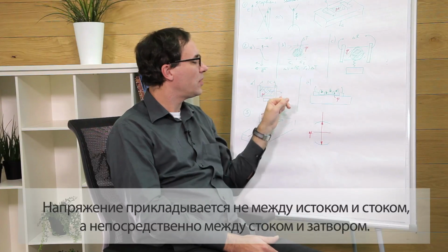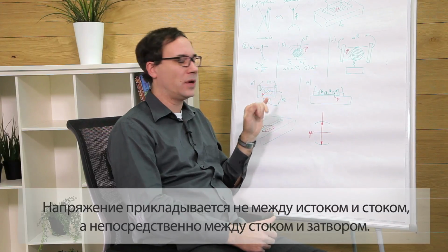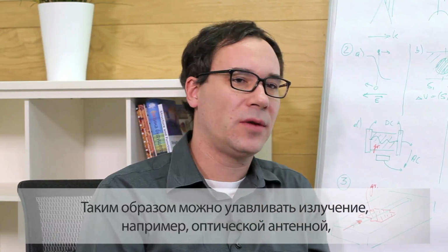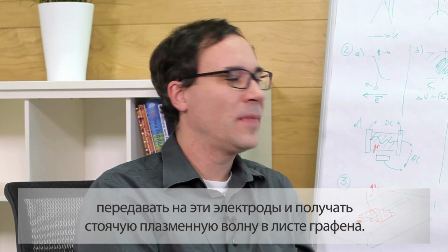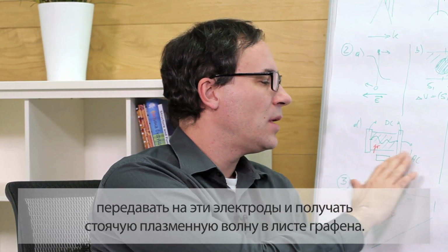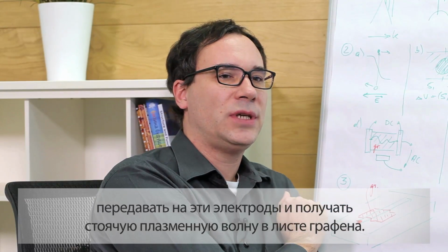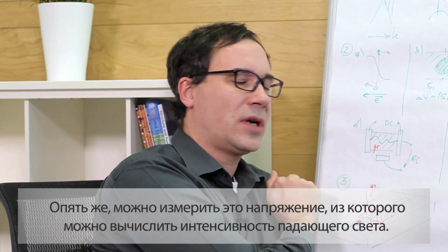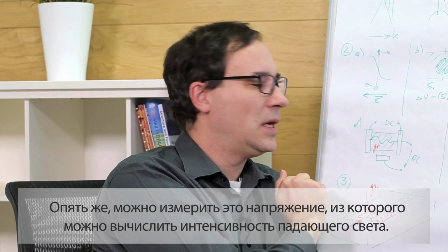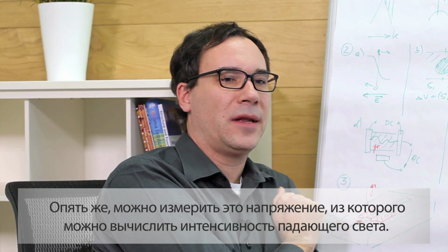A fourth method is shown here. It's quite a different geometry. You do not apply the voltage between drain and source, but between the drain and the gate electrode itself. You couple your radiation, for example with an optical antenna, to those electrodes. What it does is generate a standing plasma wave in the graphene sheet, and because of different matching at the two contacts, you generate a net DC voltage. You can again measure this DC voltage, and it gives you an idea about the light intensity.